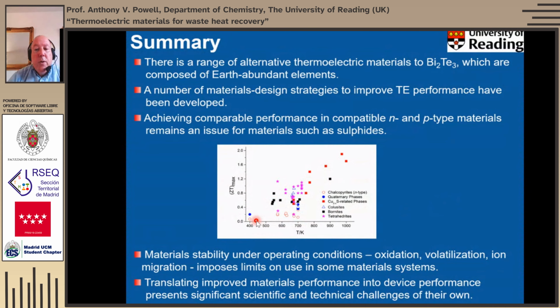Material stability is also an issue, and that applies to any of these materials I've mentioned. Skutterudites, for instance, show volatilization. Sulfur can volatilize from sulfides either during processing or operation. Ion migration, as we've seen with the phonon-liquid electron crystals, can also impose limits on how these materials are used. And then there's the whole issue of device performance, and this is not something we've done ourselves, this is something we've done in collaboration with the University of Cardiff. Device performance is a whole new issue on its own, and I think it's a whole series of research projects once the material's been developed.